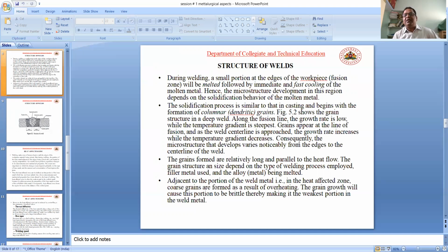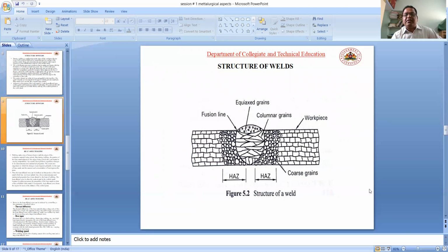Adjacent to the portion of weld metal, the area is called the heat affected zone. Coarse grains are formed as a result of overheating. The grain growth will cause this portion to become brittle, thereby making it the weakest portion in the weld metal. You can see the grain growth, that is, coarse grains are formed. So this makes the HAZ area brittle and weakest. In the diagram you can see the coarse grains, the long grains, the HAZ and fusion line. This is called structure of weld.